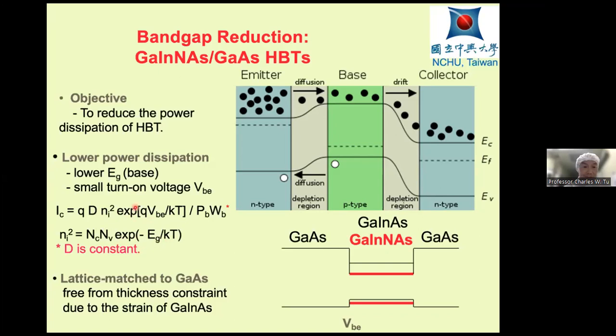The other exponential function is the base-emitter bias. So we have these two exponentials. And so for the same collector current, in order to reduce the base-emitter bias, we should reduce the band gap. Okay, so we put the nitrogen into the gallium indium arsenide base, and so the band gap is reduced. Of course, the problem here is that we have a large conduction band offset, which acts as an electron barrier. So we have to provide some grading to eliminate this barrier. But I'll not talk about it here.